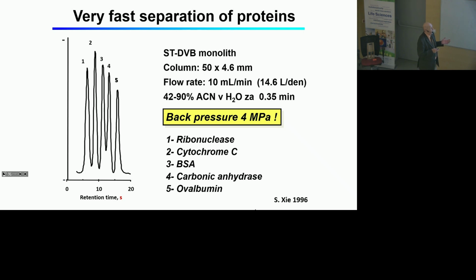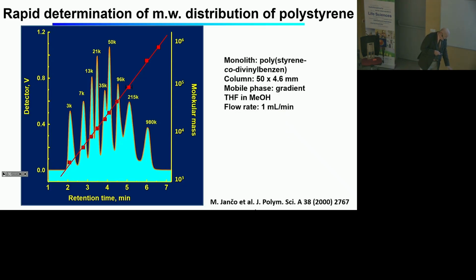When we use it for the separation of proteins, you can see that at very small back pressure, we can separate 5 proteins in about 18 seconds. This was in 1996. At that time, it was really very fast separation. We can even use this material for size exclusion chromatography, shown here. Again, typical size exclusion chromatography that is used to define molecular mass of synthetic polymers. It takes hours. Here we can do it in about 7 minutes, and as you see, the calibration curve is very nicely straight.